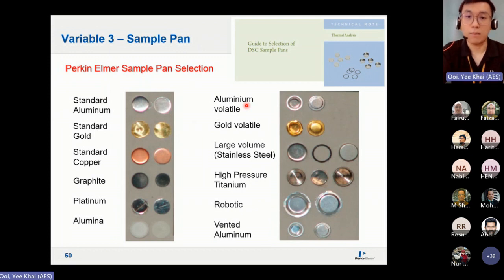Now, this is the one that I mentioned just now. Compared to TGA, you have many more selections for DSC. Okay, a standalone DSC. So the standard would be your aluminum. If you have a lot of volatile samples or liquid samples, this is the pan that we recommend, the aluminum volatile pan. Then you do have other pans, like for example, gold, copper, or even platinum. Okay, these will withstand high temperature.